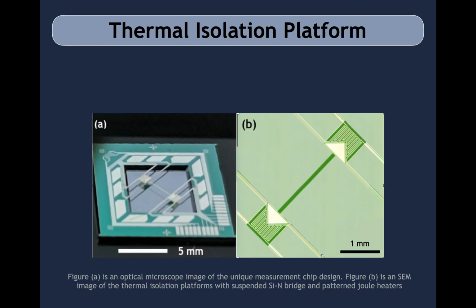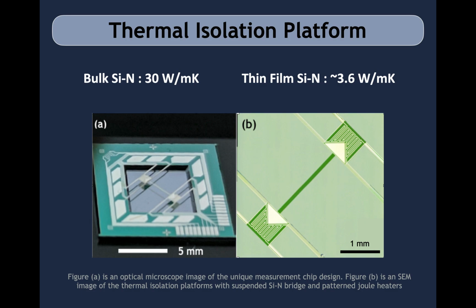For any sample, the thermal conductivity of the substrate contributes background noise to measurements. This background noise is directly proportional to the substrate thickness, so bulk samples have a much higher background than thin films. Our chip is uniquely designed to minimize the background thermal conductivity by suspending the material to be measured on a very thin silicon nitride bridge, as you can see on the slide. This suspension ensures that the thermal conductivity of the background is less than that of the sample, which allows for more accurate measurements, especially at low temperatures.